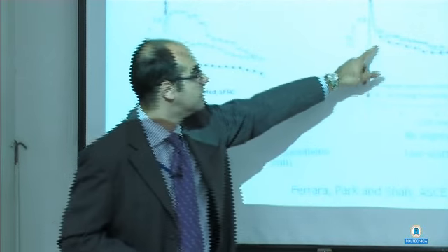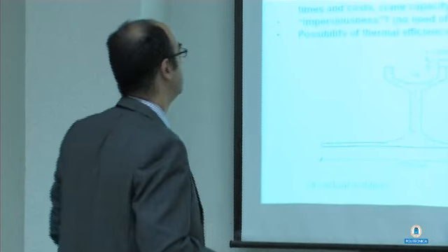They have a very narrow dispersion, and there is practically no significant segregation. You cannot avoid some settlement because the fibers have a specific weight which is about 3 times that of the suspending fluid matrix, but they were quite able to hold in suspension.